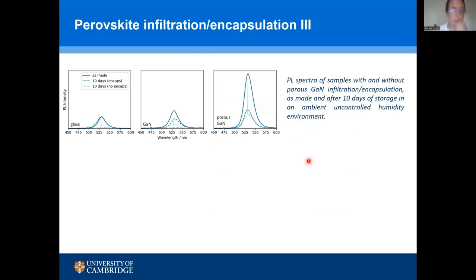And when we do that, it's really great in terms of the photoluminescence from these materials. Because normally, if you just leave these materials without encapsulation, like the example I've got here shown on glass, over a period of, say, 10 days, the photoluminescence completely degrades and you end up with almost no light coming out from your samples. And the same thing if we just put it on a planar GaN surface, again, the photoluminescence degrades.